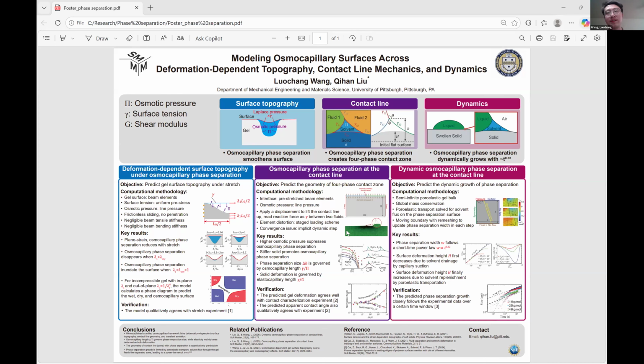We model the gel as a semi-infinite poroelastic medium. Near the contact line, the surface separation zone is modeled as a capillary-driven boundary condition. And we solve the poroelastic transport in the bulk to obtain the solvent flux at the boundary. We then use global mass conservation to convert this flux into the growth of the separated solvent volume. And we then map the volume back to the change of this phase separation width.